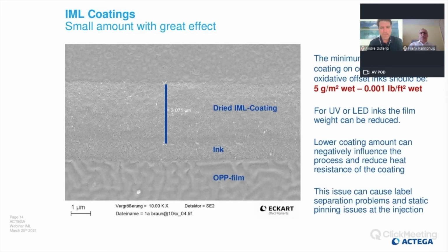Here you see a picture with a microscope of the dried IML coating. This is a water-based coating. So here you have a white layer of about 3 micron. That is a good property of a coating. It's the right way, because you have to protect the ink and the film for later mechanical stress and for heat.